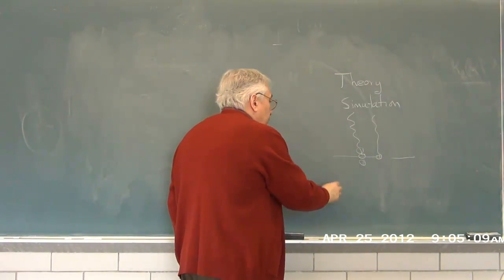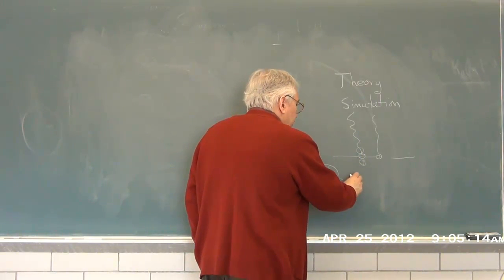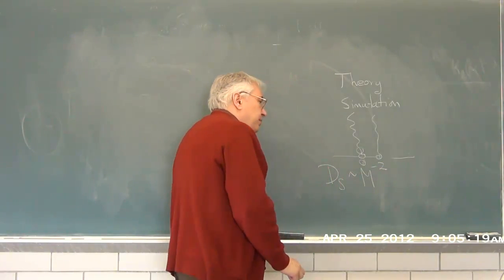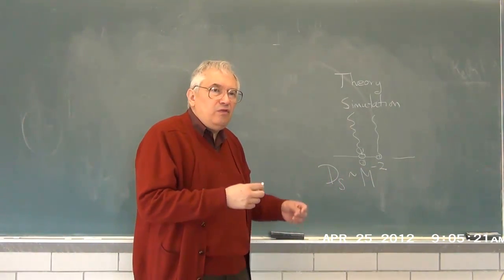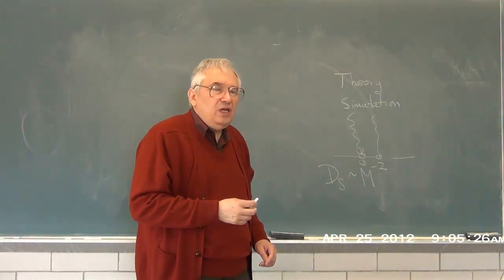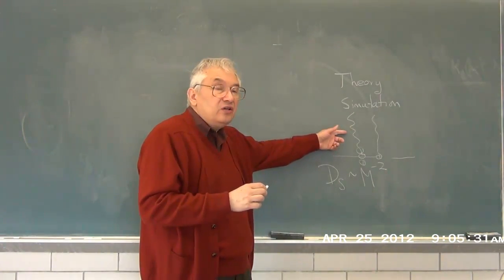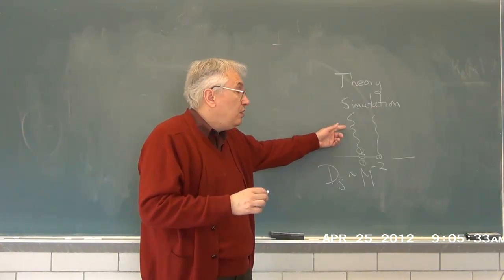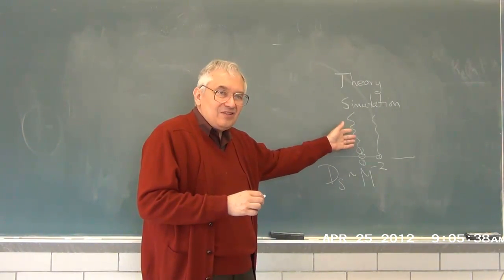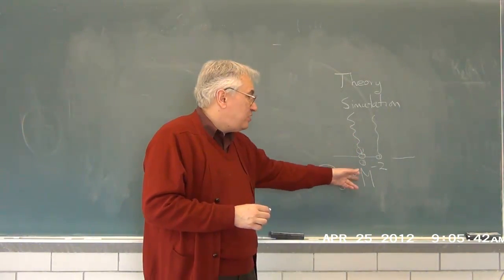And what was done was to computationally determine the diffusion coefficient of these chains, and the diffusion coefficient was found to go as M to the minus 2. Now, you will find people who claim that D proportional to M to the minus 2 is the signature that proves you have reptation. And this simulation conclusively disproves that claim for the excellent reason that these chains cannot possibly reptate because they're attached at one end. They can only move sideways, and nonetheless you see this behavior.